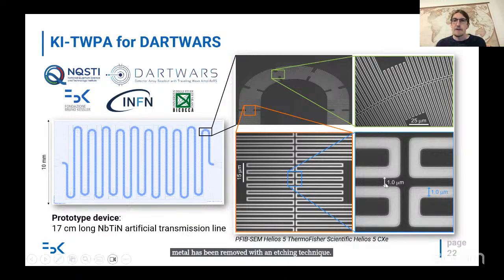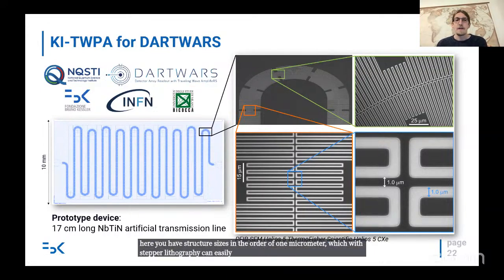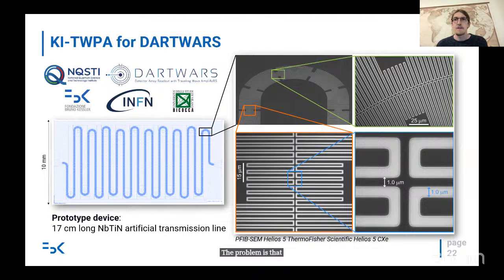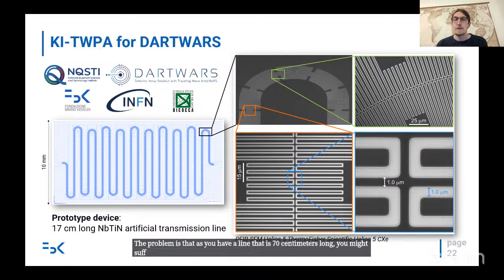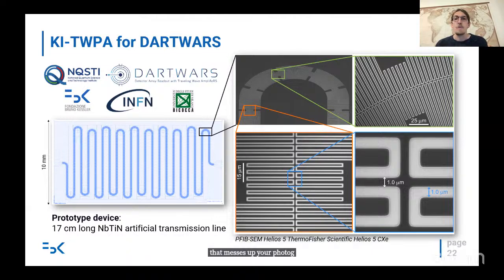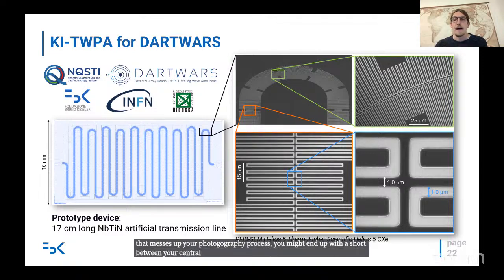Here you have structure sizes in the order of 1 micrometer, which with stepper lithography can easily be reached. The problem is that as you have a line that is 17 centimeters long, you might suffer from defects, because even the cleanest clean room is not perfectly clean. So if you have just one dust grain that messes up your photolithography process, you might end up with a short between your central line and the ground plane, and that will compromise the functionality of the device.